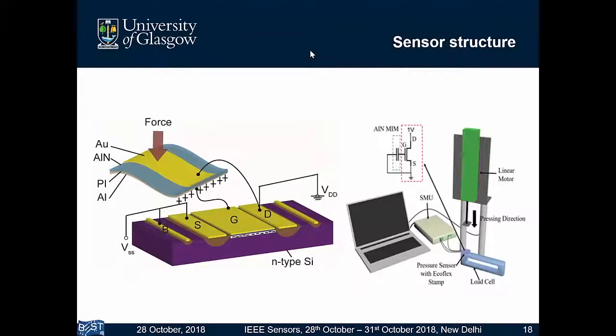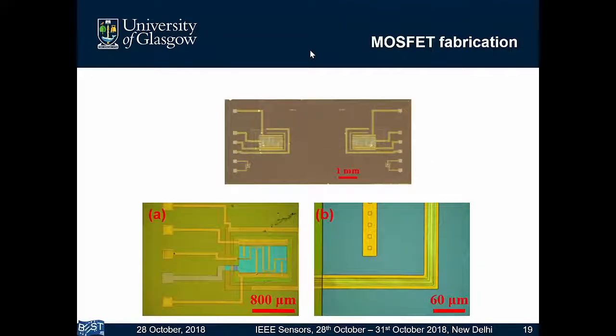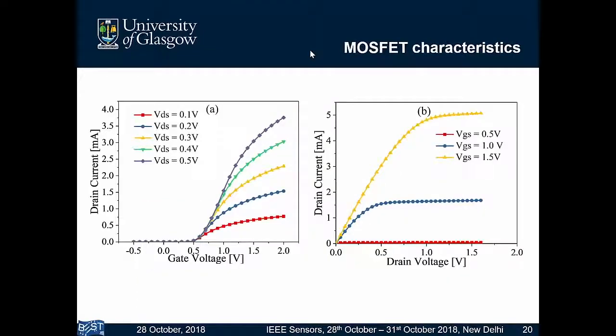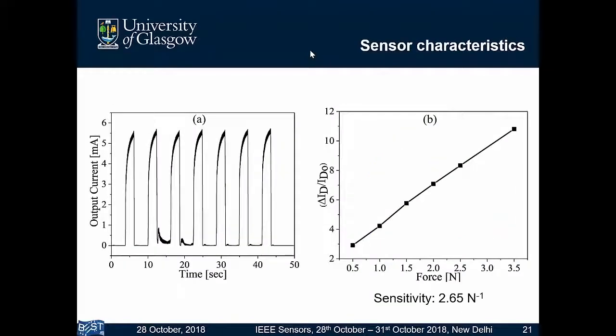To check, we attached it in an extended gate configuration with a MOSFET. For the MOSFET, we did a new fabrication run with modified parameters, because there were some issues with the previous design of the MOSFET. This shows a micrograph of a chip which we fabricated. Here is the response of the MOSFET, just to check whether the MOSFET itself is working or not. And after connecting it to the aluminum nitride, we got the response. So we received the sensitivity.